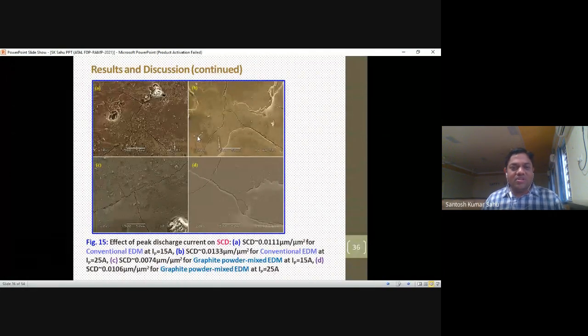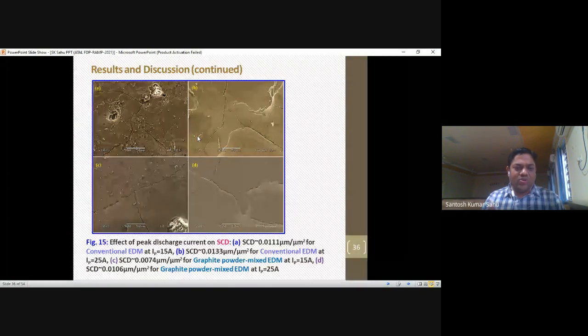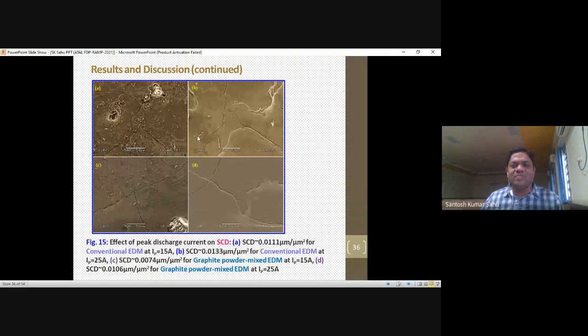And again, in figure number 15 you have to see the effect of peak discharge current on the TWR, then the MRR, then the surface finish. Then you have to know about the cracks, which should be minimum. The surface crack density is about 0.0111, and after adding graphite powder you see the surface crack density is about 0.0106. That should be minimized, as seen by viewing figures A, B and C, D.